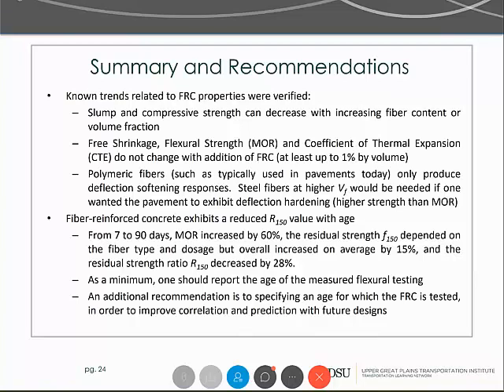The steel fibers, however, did have a deflection hardening, particularly when you went to that 1%, which is, again, something some structural designs are looking at, ways to switch out rebar and use steel fibers instead. This is going more towards that route. But for pavement design, I don't know if anyone's looked into seeing if deflection hardening will actually be beneficial, but it is a thing that's unique about the steel fibers, that they tend to go into that deflection hardening mode, especially at later ages for sure.